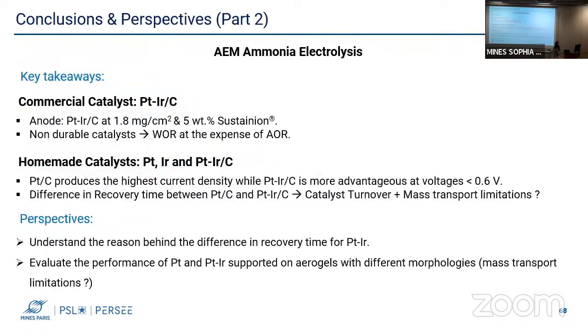As for the second part, using a commercial catalyst, the best anode conditions were obtained with platinum iridium on carbon at a loading of 1.8 milligram per centimeter square and 5 weight% of Sustainion. The catalysts were not really durable because the water oxidation reaction was taking place at the expense of the ammonia oxidation reaction. For the homemade catalyst, platinum on carbon produced the highest current density, while platinum iridium on carbon was more advantageous in the low potential region.